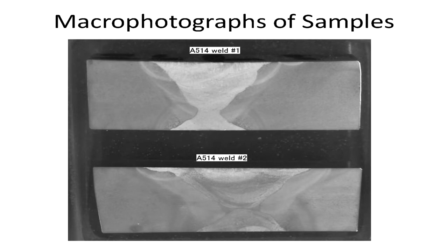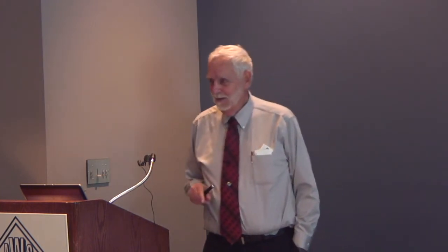Now, I ground off the weld and got it ready to be cut into the coupons, and I noticed some porosity. And I noticed a little, and so what I did is I did a repair weld. Can you see the repair weld right there? And there's another one right there. It's a different color. And when you hold it in your hand, you can see it better. And that's so, the metallurgy doesn't lie. The microstructure busted me.